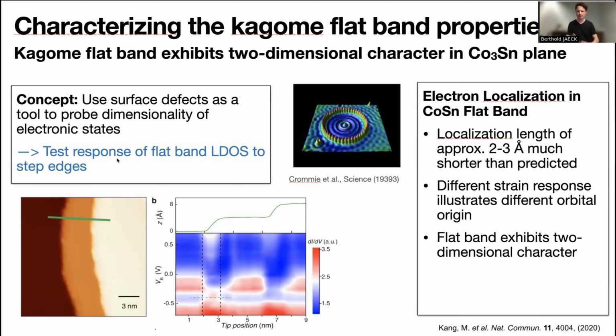Intuitively, you would expect that a 3D electronic state that extends into the bulk of your sample doesn't really care about the presence of step edges. And this intuition is somewhat consistent, for example, with the electronic states at very low energies, which can be ascribed to the dispersive Kagome bands. Here you can see those states barely care about the presence of the step edge, which is basically in this region and this region, when we take a line cut along these 2 step edges.